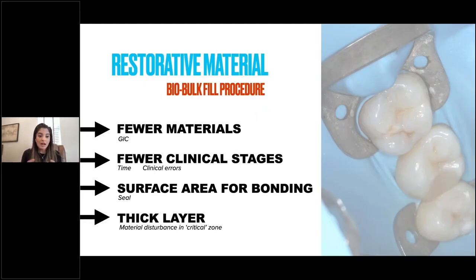I also feel like I've now got a thick layer of the Biodentine in the critical area, so over the pulp. And we are less likely to disturb that when putting the coronal composite on. So in the case I just showed you, you could see that I had a very thin layer of Biodentine, and then I put a resin modified GIC on top. And I'm not that happy about that because I don't want a resin-based material near the pulp. And so we've taken that area out. We've now got a really thick layer. And if I do a single visit procedure and I put a composite on top, I'm not doing anything close to where it's very critical near the pulp.